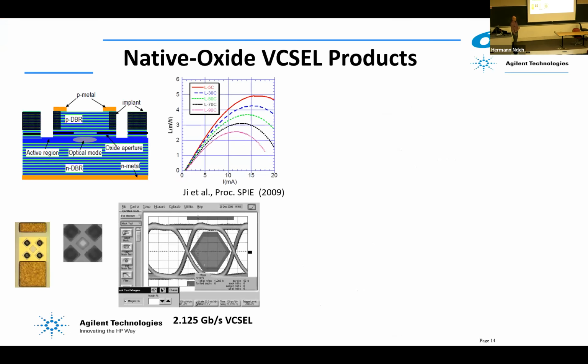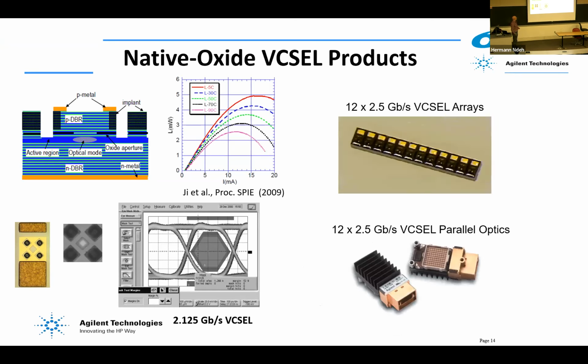So the first commercial applications of these were for communications devices, and this is work that we actually did when I was at Agilent Technologies, where we developed the first commercial 2+ gigabit per second VCSELs. And again, these utilize the native oxide on the edge. So again, we're oxidizing in from holes etched in the surface and creating an aperture in the device itself. And we ultimately scaled these to arrays of 12 devices, and these were used prolifically for data center interconnects, and they still are today, albeit at higher data rates.